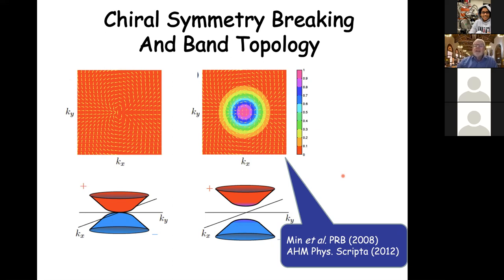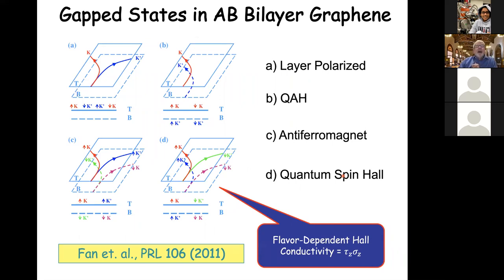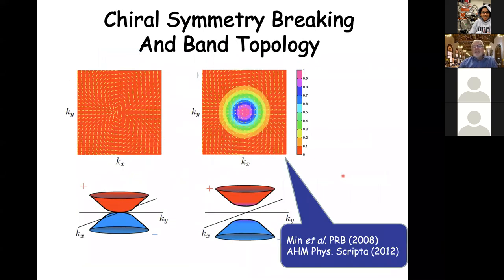Similar things happen in twisted bilayer graphene, except that the correlations or interactions are made more important by narrowing the bands. So in bilayer graphene, as you can see here in this cartoon, the Bloch vectors that represent the two-layer system, as a function of momentum in this broken symmetry state, when you integrate over momentum space, when you cover a certain area in momentum space, then you cover basically the entire northern hemisphere of the sphere.